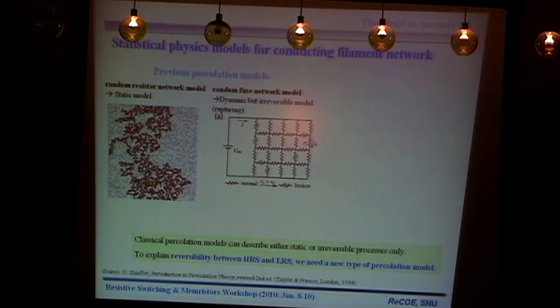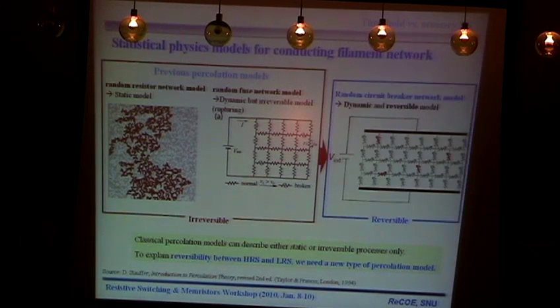So this can explain the irreversible process, dynamic process. However, in the resistive switching, we need reversibility because we have to change between the high resistance and the low resistance repeatedly. So these two models are not sufficient. That's the reason we propose the random circuit breaker network model.